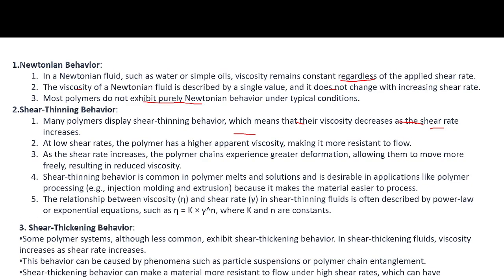For shear thinning behavior, the polymer's viscosity decreases with the shear rate. At low shear rate, the polymer has a higher apparent viscosity, making it more resistant to flow. As the shear rate increases, the polymer chains experience greater deformation, allowing them to move more freely, resulting in reduced viscosity. Shear thinning behavior is common in polymer melts and solutions and is useful in applications like polymer processing, injection molding, and extrusion because it makes materials easier to process. The relation between viscosity and shear rate for a shear thinning fluid is described by a power law: viscosity equals K times shear rate to the power n, where K and n are constants.